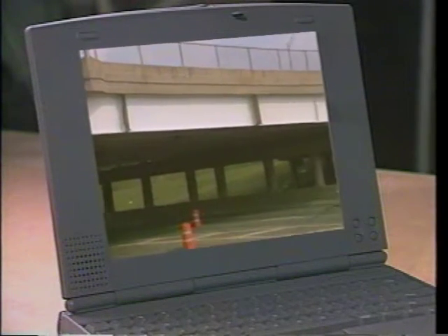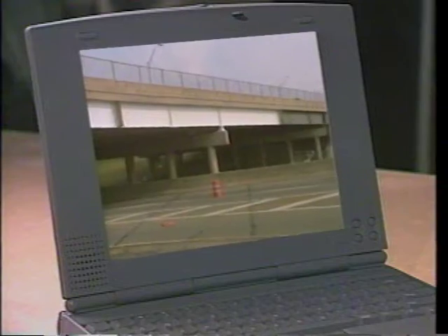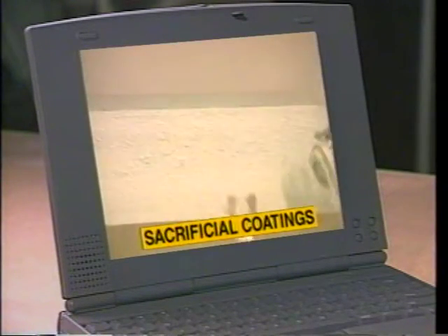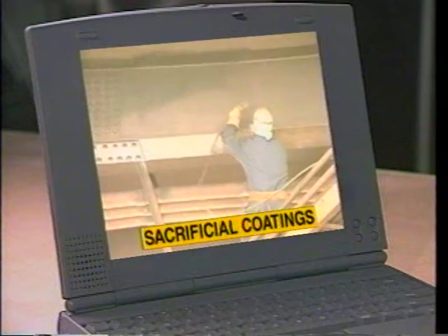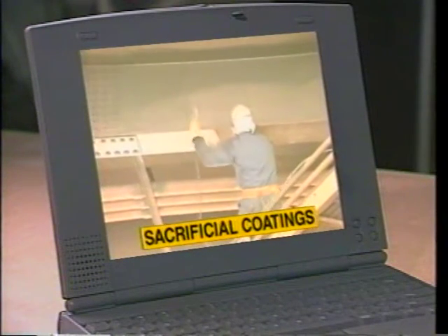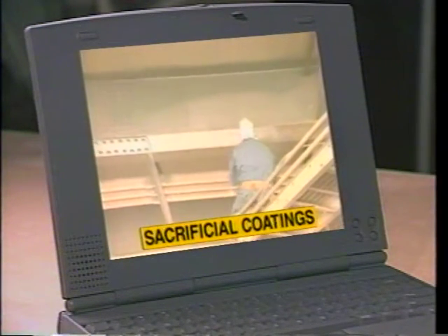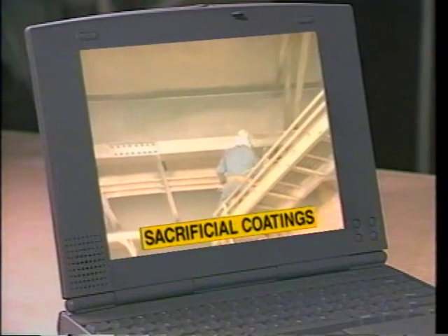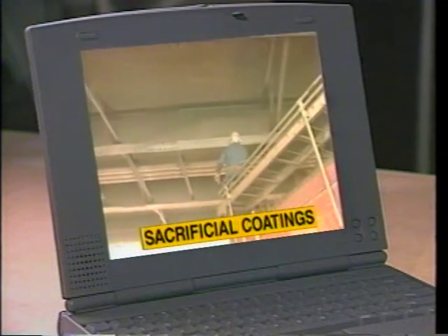In other words, to a limited extent, the metal particles corrode at a faster rate than the metal the coating is designed to protect. The most common example is a zinc-rich coating applied to a steel substrate. The zinc, being higher on the galvanic series than the steel, is the anode. It will be sacrificed. That is, the zinc will corrode in place of the steel. Furthermore, as the zinc coating breaks down, it leaves byproducts which further inhibit corrosion of the steel substrate. Obviously, a properly specified and applied coating system may be your best defense against the destructive effects of corrosion.